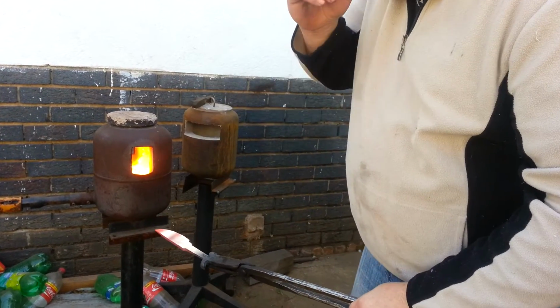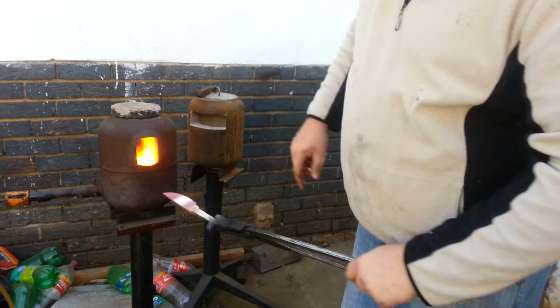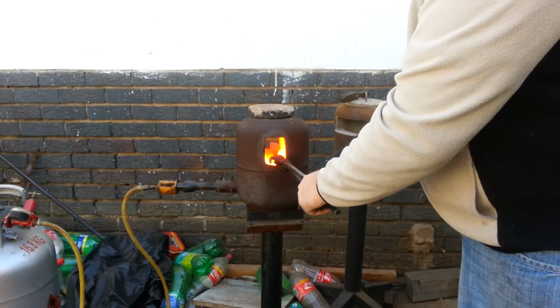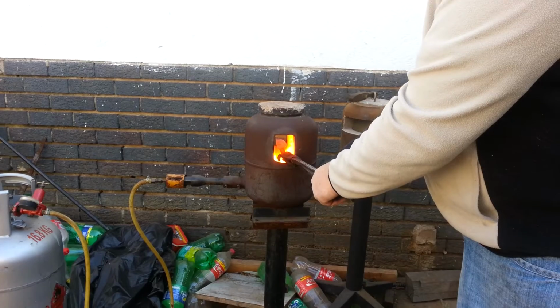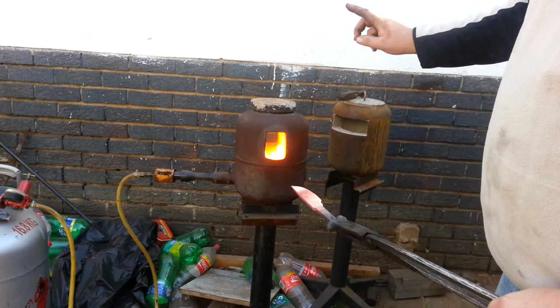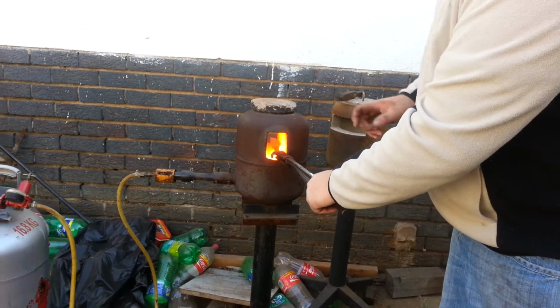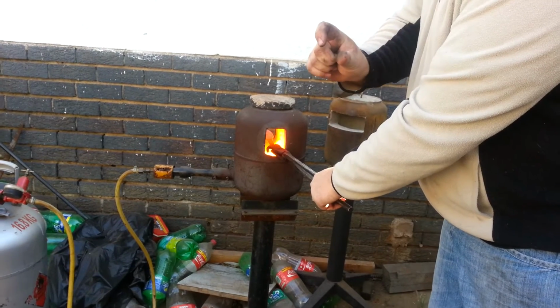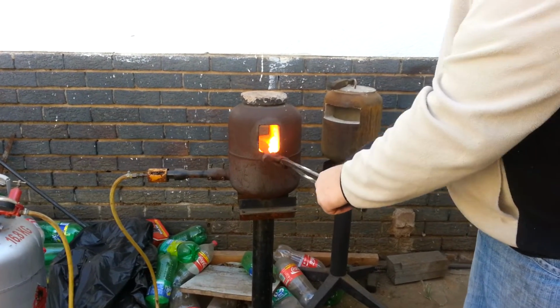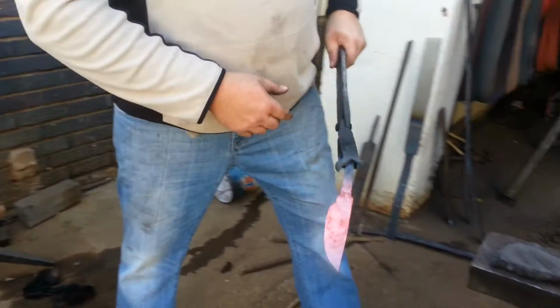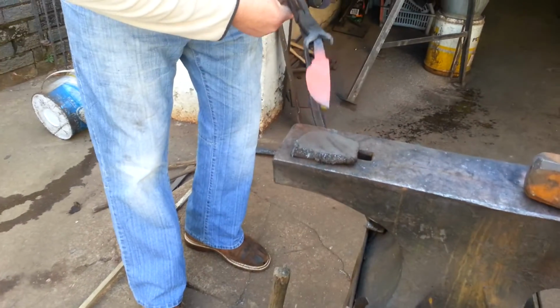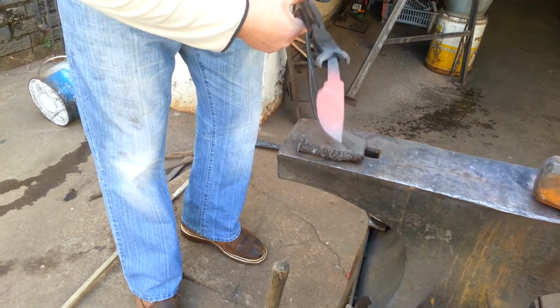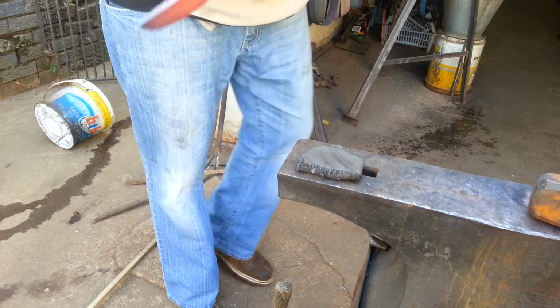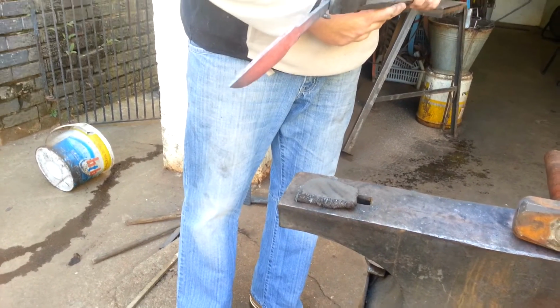Now there's a hole on the other side of the forge. I put the tip through to the other side. Because the tip is thinner, it heats up faster. By putting it through the other side, it's actually not receiving a lot of heat, allowing the ricasso, that's the thick part of the knife just before the tang, to heat up faster. We've got nice even heat. It doesn't stick to the magnet. I will now repeat that 2 more times before I take it for grinding.